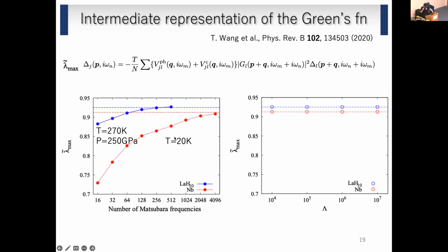And yes, this is one demonstration. Here we calculate the eigenvalue of this Eliashberg equation, and when this maximum eigenvalue becomes 1, that temperature corresponds to the transition temperature. If we do the standard calculation, I'm showing two examples: LaH10 and elemental niobium. The Tc of elemental niobium is about 10 Kelvin, so it's quite low.